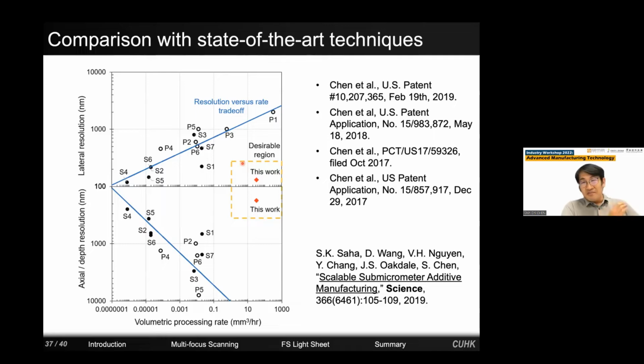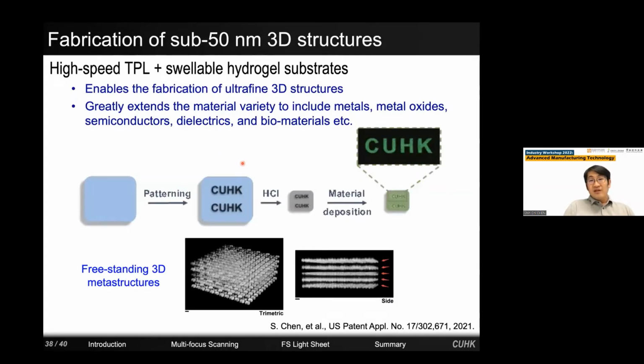On the other hand, many metastructures, especially in visible light applications predicted by scientists, require features below 50 nanometers. And that's some area that we are working on right now. And with limited time, I can briefly talk about the idea. Essentially, we use a hydrogel as substrate because hydrogel is swellable. So we print structure on the hydrogel in expanded states using our light sheet system.